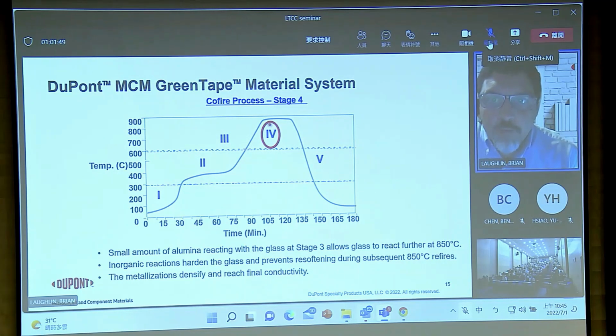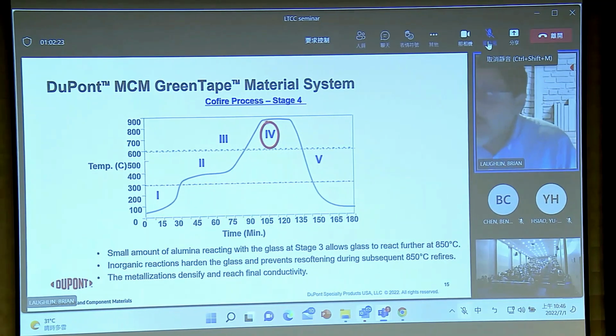And then you reach a maximum temperature where you are really just trying to get all of the inorganic reactions to go to completion and densify the system as much as possible. So usually that's about 850. You can probably fire a little bit lower. It may be advantageous to fire a little bit hotter. Then comes in the design of your process for what you need the conductors to sinter to, what you need the dielectric constant to be, what you need the dielectric loss to be. A lot of that's happening for where you set the height of the temperature of the shelf and the length of this shelf.